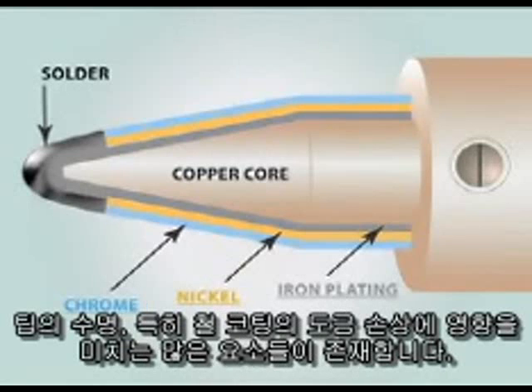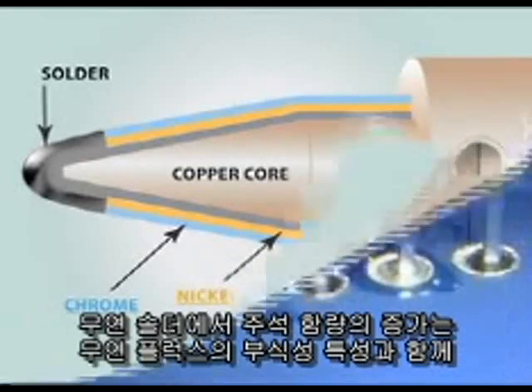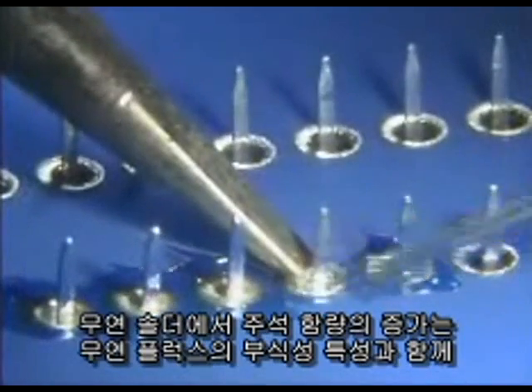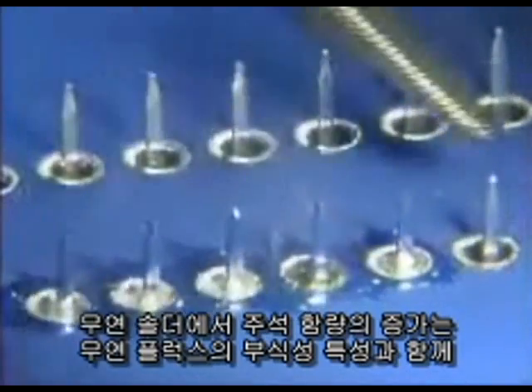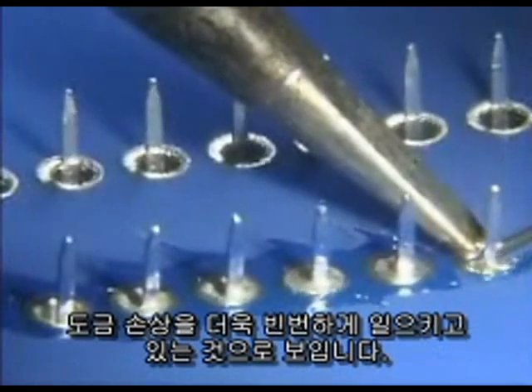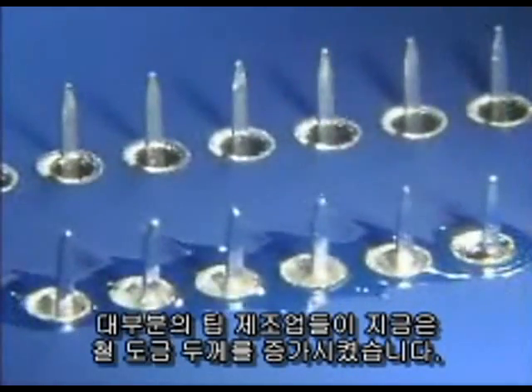There are many factors that will affect tip life, in particular, plating failure of the iron coating. The increased tin content of lead-free solders, along with the more aggressive nature of the lead-free fluxes, may cause a plating failure to occur more rapidly. Most tip manufacturers have now increased the iron plating thickness in the hope that this will prolong tip life with the more aggressive high tin content of the lead-free solders.